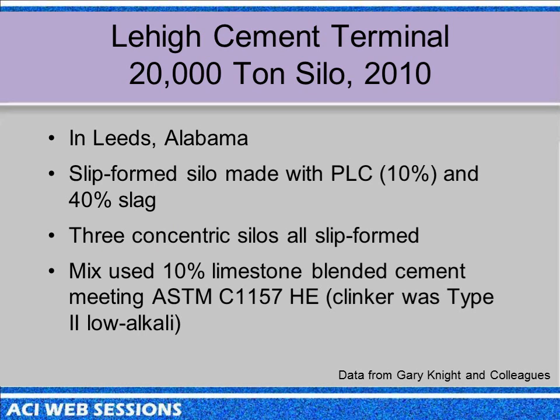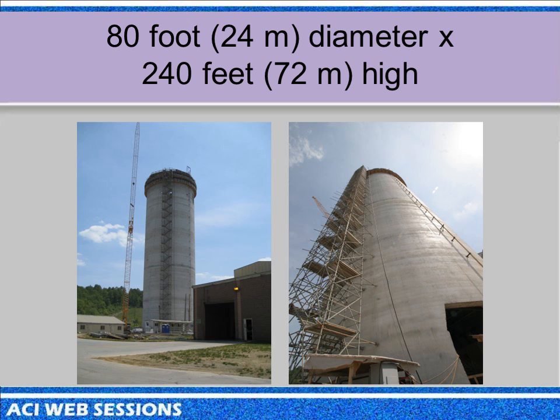Heidelberg, or Lehigh, has also been producing limestone cements under the same 1157 spec for a number of years. They've done a number of projects. One of them was a silo, 20,000-ton slip-form silo at one of their own operations in Alabama. And they used 40% slag together with the 10% limestone, so they're replacing over half the clinker here. 3 concentric silos using a Type 2 low-alkali clinker, and courtesy of Gary Knight and his colleagues there.